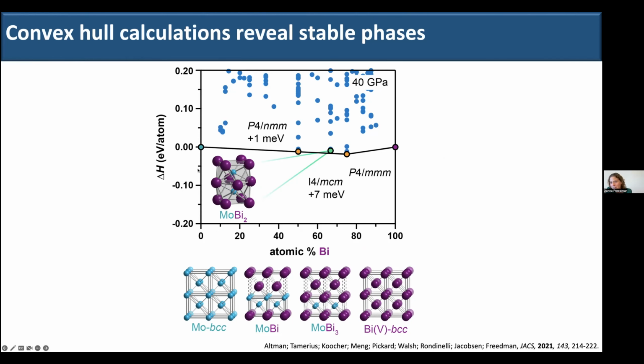And this is, of course, infuriatingly at 0 Kelvin. You can tell I'm an experimentalist, right? Because I'm complaining about 0 Kelvin. Because this is at 0 Kelvin, we're not just looking at the points on the convex hull, but also the points that are slightly above. Because within a given range of error, we expect that because we're doing this at high temperatures, that's going to perturb the thermodynamics of the system as well.